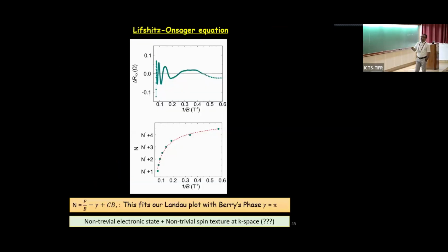So when you plot our data, Landau index as a function of 1 over B, it shows a completely nonlinear behavior, and this could only be fitted by using this formula. And this gamma also gives you the idea of what the Berry phase is in terms of your electronic structure, and we found that we also have a Berry phase pi in the system. So there are 2 points.